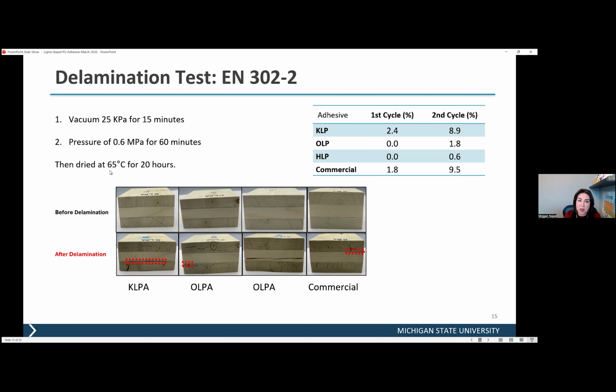And after that, we're going to put that into the oven at 65 degrees C for 20 hours to fully dry. After that happens, what we usually do is look at the delamination. The delamination is basically delamination all around the area of the adhesives that we have, like for example, these sections that we are seeing. These are samples before the delamination test. This is after. And we measured the area after the first cycle and after the second cycle.